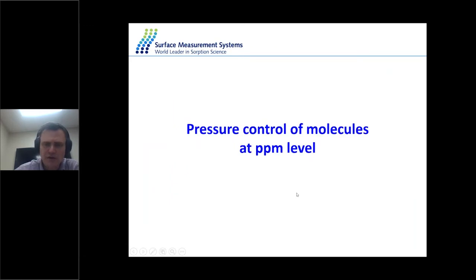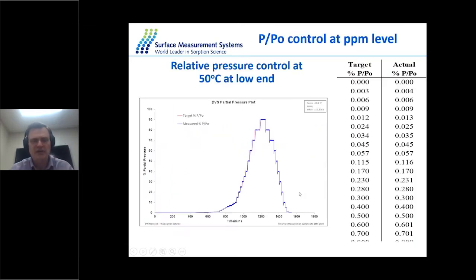Now let's move to an example of adsorption data, just to demonstrate the level at very low partial pressures. Here we look at the partial pressure control of 2-propanol at 50 degrees. At these very low partial pressures, you can see a more or less straight line. But if you look at the absolute values of target and measured P over P naught, we can go to extremely low values, 0.003, 0.006, and still detect a change in the mass.